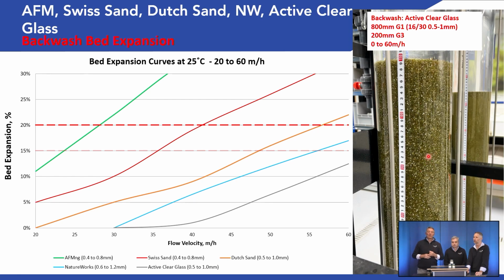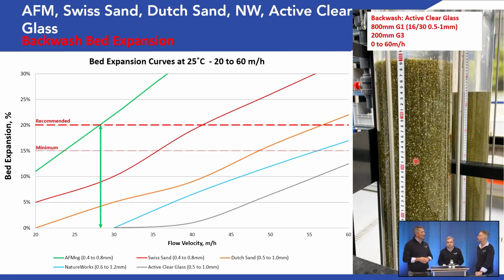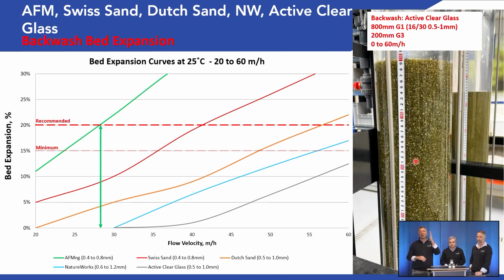And why do we show this? Because in the DIN norms, they tell you need 10% of bed expansion to have a good result, and we disagree with this. We say you need minimum 15, ideally 25, or the higher the better. So we took here 15 or recommended 20 to show, with what media you need what backwash velocity to get to this recommended 20% of bed expansion, where we can assume you have fluidization.